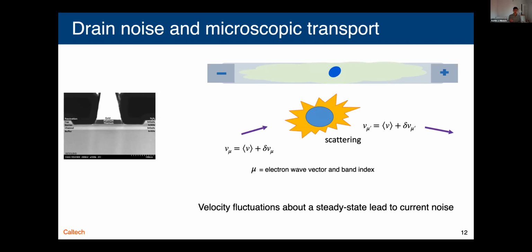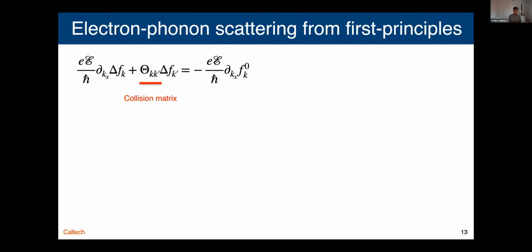So this type of problem stimulates efforts to understand high field transport in semiconductors without requiring assumptions regarding the scattering mechanisms for electron-phonon scattering. And that is indeed possible. And due to time, I'm not going to go into all the detail, but we have this Boltzmann equation, and we know now how to compute the phonon-mediated scattering elements for this matrix. And the low field calculation is now a standard procedure.